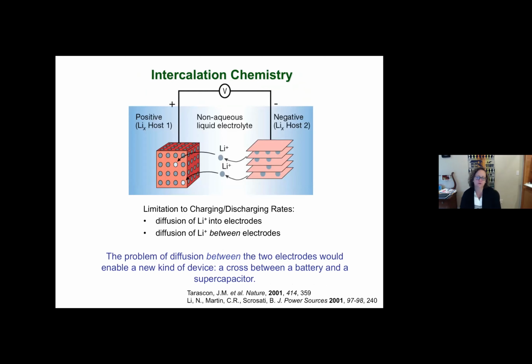Okay, so you all know how batteries work. I know everybody listening in this webinar is an electrochemist. The reason I'm showing this particular graphic is because I want to highlight that the way I think about batteries is really tied to diffusion rates. So certainly solid state diffusion of ions from the surface of an electrode to the center of that electrode is slow at room temperature. But also the distance between the electrodes is really important. And so we already know that if we make very high surface area electrodes, we can achieve pretty fast charge rates within that electrode, but the distance between the two electrodes is still a significant challenge.